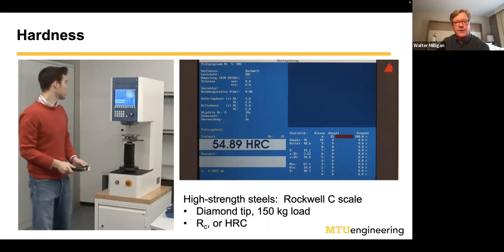And this is the standard way that we measure the performance of things like knife steels. Most knife steels are going to have the Rockwell C scale, which is what we showed on the Hori Hori. What that means is that the indenter is a diamond tip and 150 kilogram load, and it's reported as a hardness of HRC, or sometimes the symbol capital R subscript C for Rockwell C.